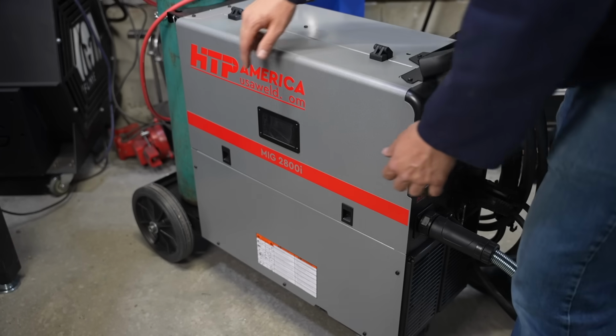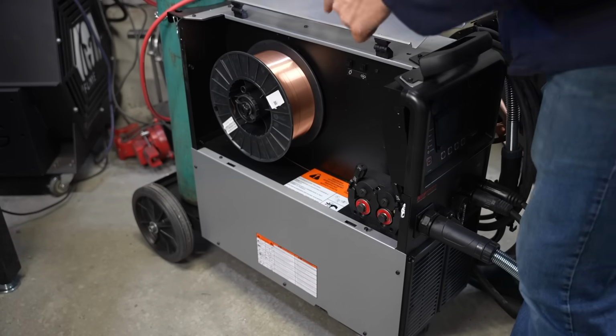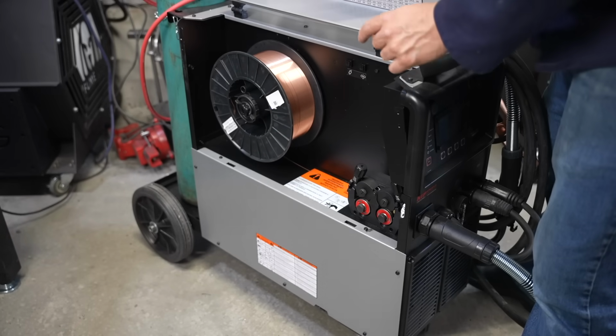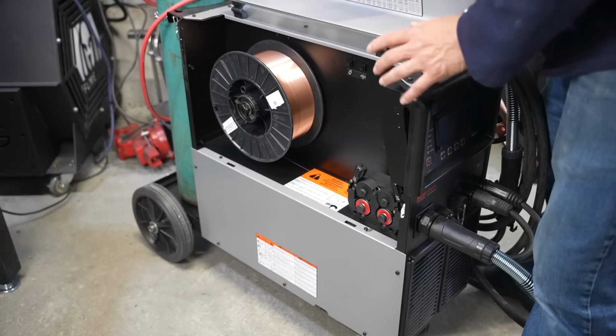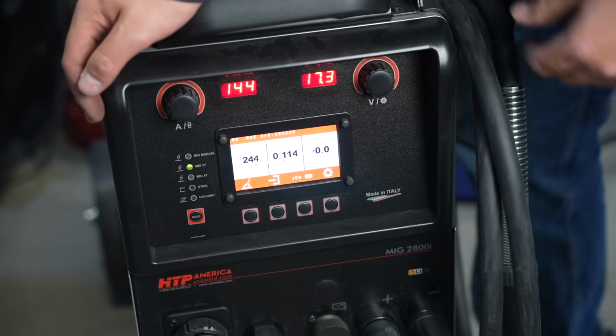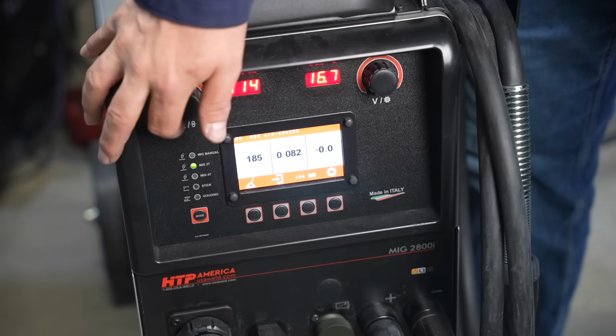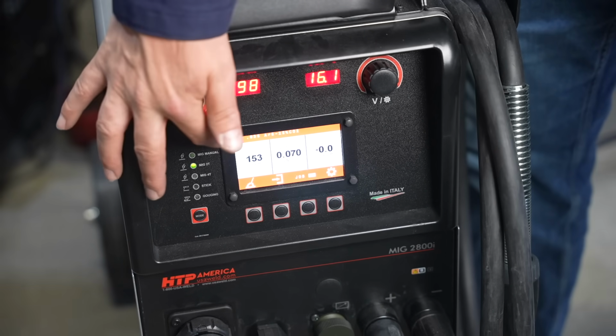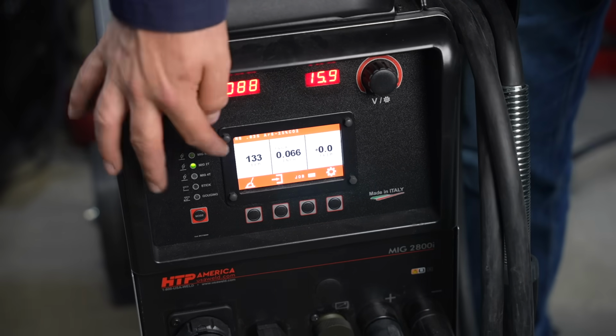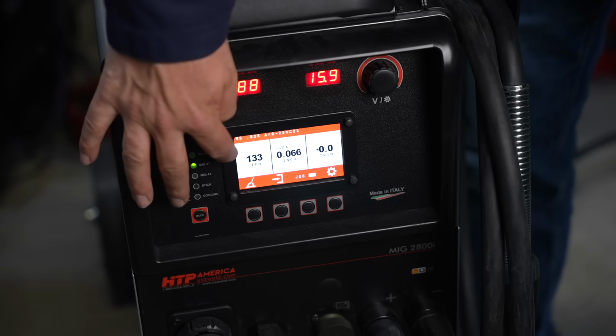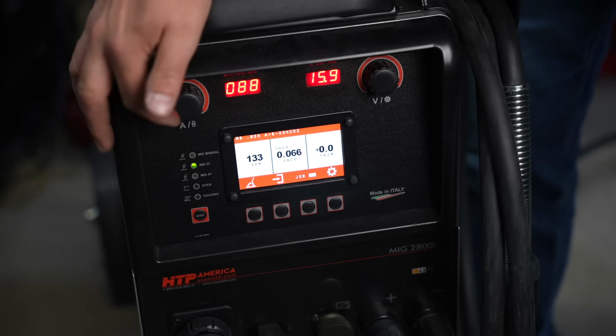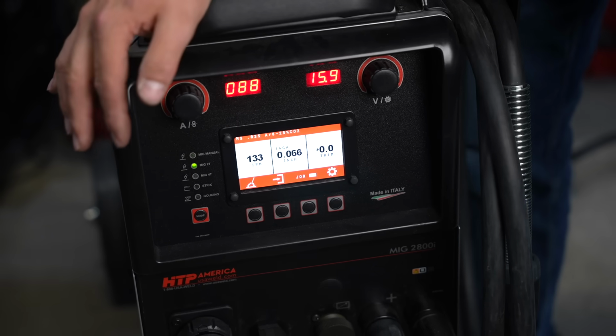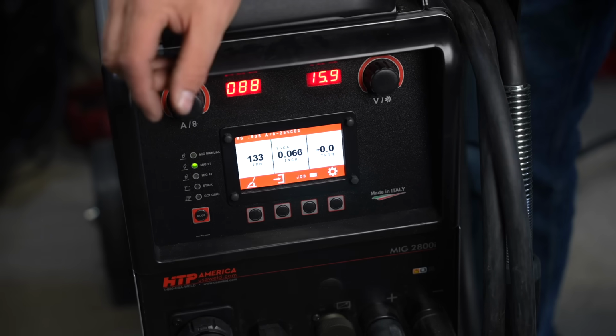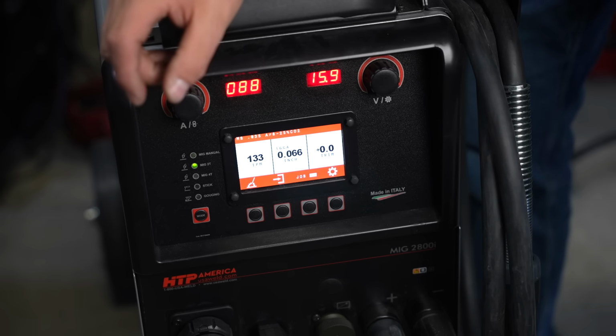Now I'm going to switch over to the big MIG here. I have some .035 here, and we'll also load in some .045 in a minute for the upper level of thickness that we'll look at. Now, the dynamic of the arc is pretty similar on these two machines, but notice with the larger diameter wire, it's recommending a much lower setting, right around 130 inches per minute for 16 gauge. So a little bit of a difference there, because the larger the diameter of wire you have, the more amperage you get for a given wire feed speed.